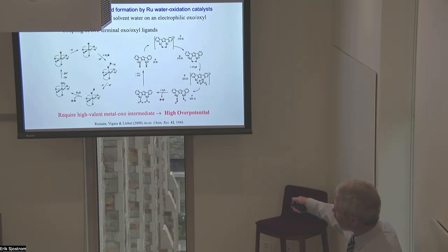Let me just take you through it. Here is the high valent metal oxo species, which is attacked by the solvent in a nucleophilic attack to form an O-O bond. And in this case, one oxygen comes from the oxo group, one comes from the water molecule. So the oxygen that's evolved has one of each label, which is a diagnostic that one was from a nucleophilic water and one was from the oxo.